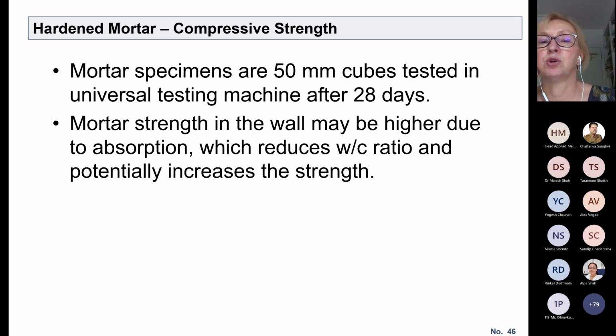So the test is done based on mortar specimens, which are 50 millimeter cubes, similar to testing of concrete cubes, but these cubes are smaller, and they're tested in universal testing machine after 28 days. So mortar cubes are cured in the same way as concrete cubes, and mortar strength in the wall may be higher than those tests because of this interaction of the bricks and mortar. Because when mortar is fresh and the bricks have higher absorption, they absorb water from the mortar, which causes the mortar strength to increase, but bond may decrease in reality.